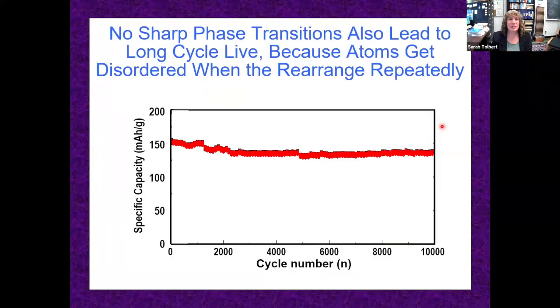Okay, so I said not having phase transitions makes things cycle longer. Does that also work with this system? And the answer is yes. We see incredibly long cycle life in these molybdenum disulfide systems. This is 10,000 cycles with almost no loss in capacity. And this is really what you need for grid level storage. When you build a battery into grid level storage, you want it to be able to cycle again and again without having to pay the money to replace that battery on the grid.